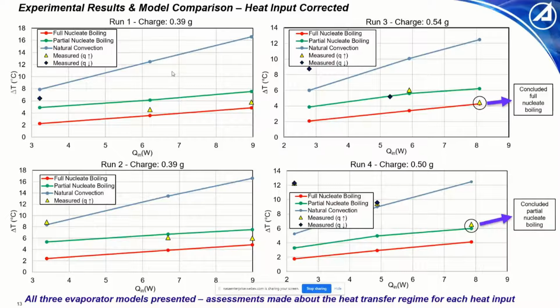One important thing to note, which I'll touch on later, is the wide range in wettability, surface roughness uncertainty due to our 3D printing, and any contaminants. They create a really wide range of partial nucleate boiling and natural convection behavior, so at similar power levels we get very different measured heat flow values.